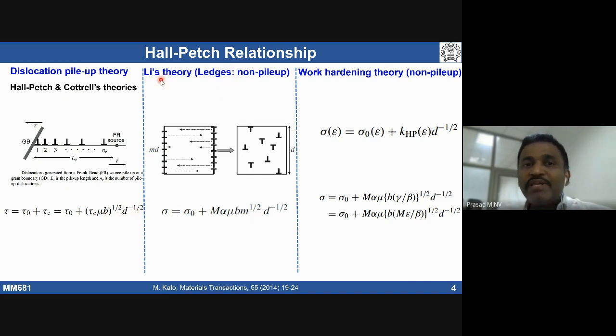So later people came up with Li, and some other work hardening theories and composite models to explain how dislocations play a role in terms of a grain size effect. According to Li's theory, boundaries in a polycrystalline material contain some ledges - very tiny ledges present in the boundaries. Those are sources for dislocations. Dislocations get generated from the boundaries, and those dislocations traverse into the grain, where they can form some forest dislocations within the grain. Some dislocations will be left out as forest dislocations for further dislocation.